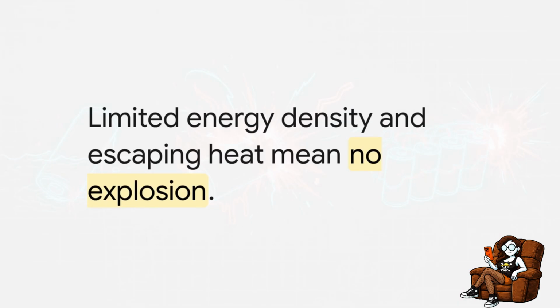Well, because it's a single, isolated lithium-ion cell. The peak amperage might start at 300, but it rapidly decreases in just tenths of a second because its overall energy density is limited. And more importantly, it's sitting all by itself. The heat it builds up can easily escape right through its metal casing into the ambient air, which in this specific test environment was sitting at a cool 7 degrees. A single cell simply doesn't have the energy density to push itself past the point of no return when the heat actually has somewhere to go.